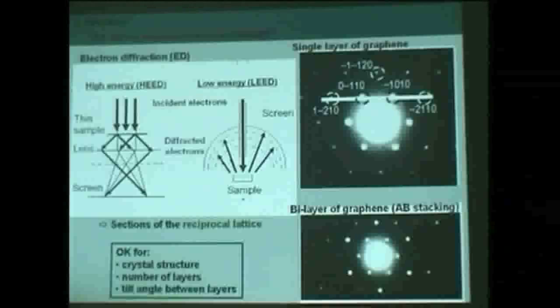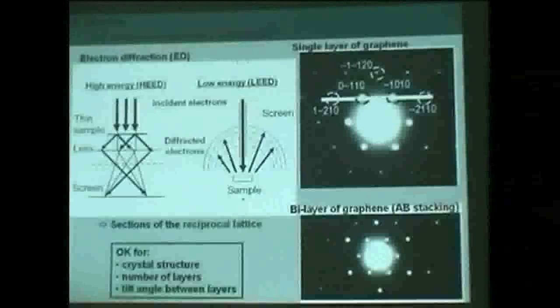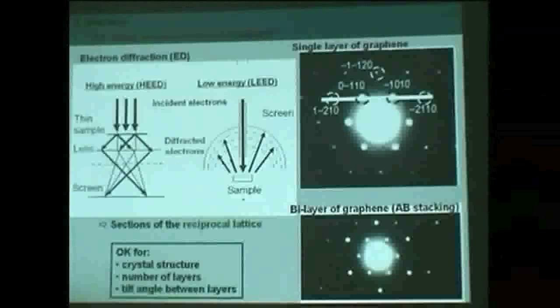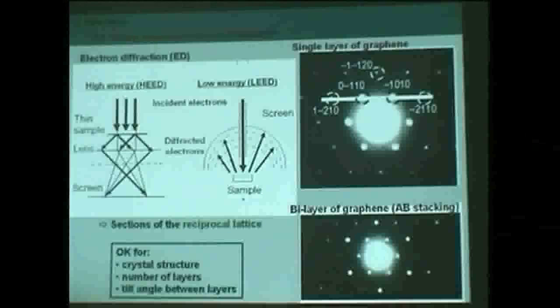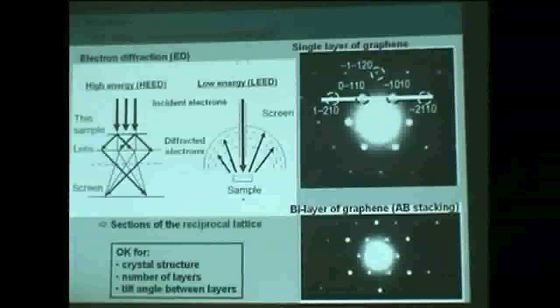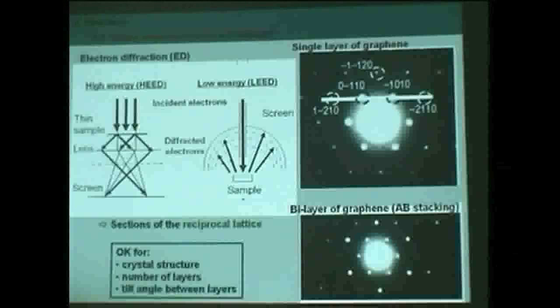But there is this interference effect between the electrons diffracting by one layer and the other, and then it changes the intensities of each dot. But it does not create new dots. No new dots, just change the intensities because it's just the same plane without difference of orientation. They are oriented exactly the same, these two graphene planes.